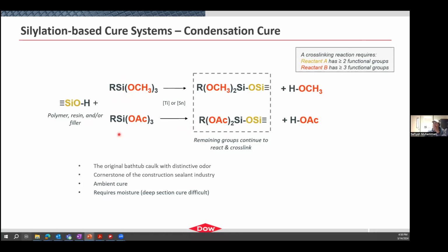And so you can take these reactants here, use them as a cross-linker, and begin to build in your PDMS network, and often through the aid of a catalyst. So this is actually the type of chemistry that you use when you think about bathroom caulking, the seal that goes around your bathroom type of material. This is the chemistry that is within it.